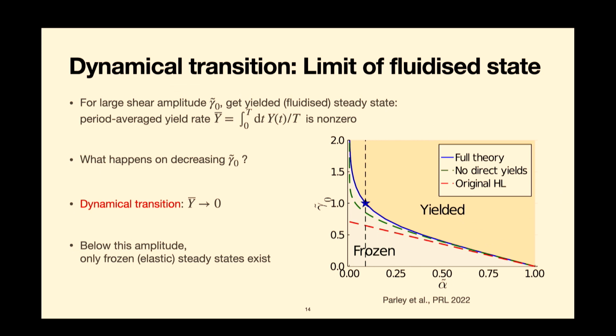Okay? So the way you can sort of understand this is you could say, well, if I look at the yield rate and I average it over one period of my oscillation, which I'll call capital T, then up here that's going to be non-zero because I keep dissipating energy, I keep having yield events. Okay? And then as I lower the amplitude, what can happen is that at some point this yield rate goes to 0, and that's this dynamical transition that I've mentioned. Okay? So that's when the system basically freezes.